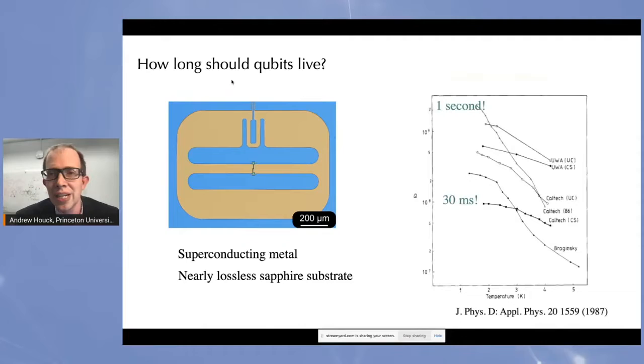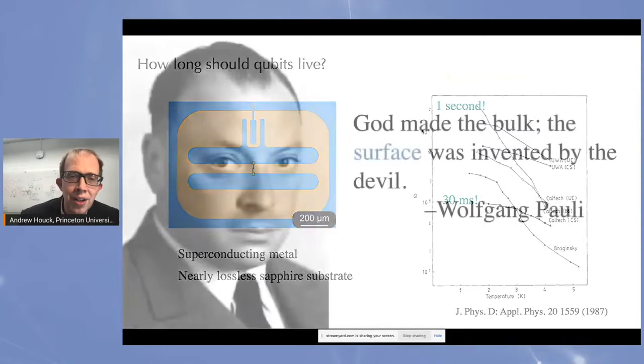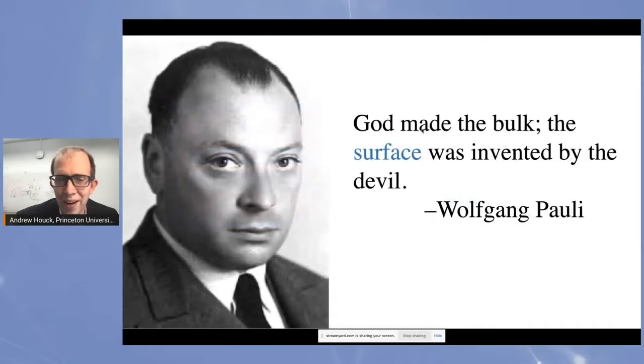And indeed, if you dig into some old literature, you can find that the predicted coherence times should be at least 30 milliseconds, if not all the way up to a second. So why are we stuck at 100 microseconds if these bulk sapphire crystals are so good? Well, it turns out that Wolfgang Pauli had the answer many, many years ago, which is that God made the bulk, but the surface was invented by the devil.